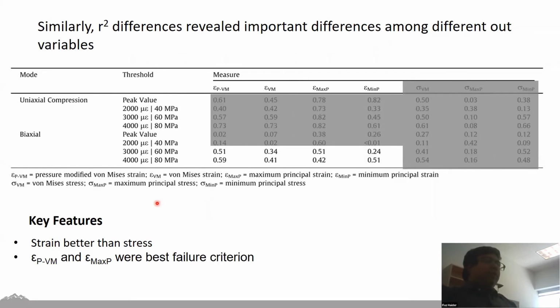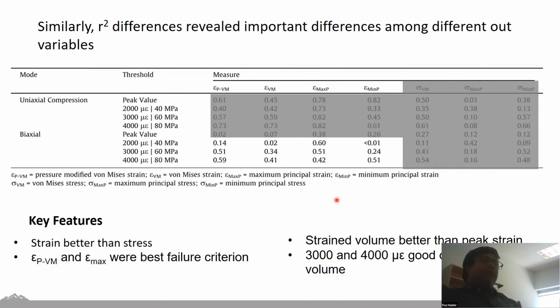Another thing that we found is when we looked at different failure criteria, it seemed that both the pressure modified von Mises strain and the maximum principal strain were equally good and equally robust. And that becomes most evident if I draw your eye to the biaxial loading case, which seemed to be the most challenging one to predict. And again, both of these failure criteria did reasonably well at predicting this situation. I already talked about the fact that strained volume generally worked better than peak strain. But another thing that we did identify in this study was that because before we didn't really know what an appropriate cutoff for strain volume would be, our data here seemed to suggest that 3,000 or 4,000 microstrain were sensible cutoff values.